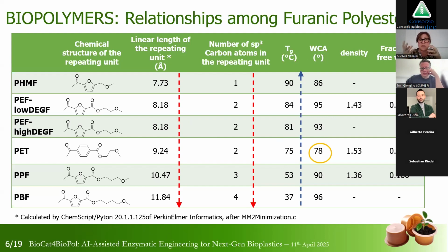This is evident when we consider the water contact angle. In PET, we measured a water contact angle lower than 90 degrees, indicating that PET is a hydrophilic material. This happens because the ester groups present in the chemical structure of PET are able to positively interact with the water molecules.